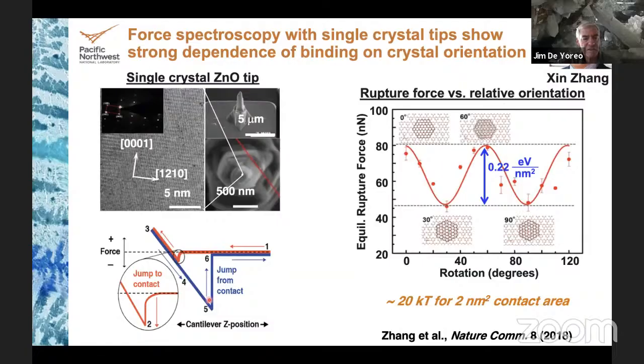And measuring this deflection and knowing the spring constant, you can get the rupture force for pulling the two surfaces apart. And we did this in an AFM with a rotational stage so that we could measure the rupture force as a function of rotation. I don't want to get into the details of how you make sure that you're measuring the rupture force at equilibrium, which is infinitesimal pulling rate. You'll just accept that this is the equilibrium rupture force, and therefore it's equivalent to the equilibrium free energy.